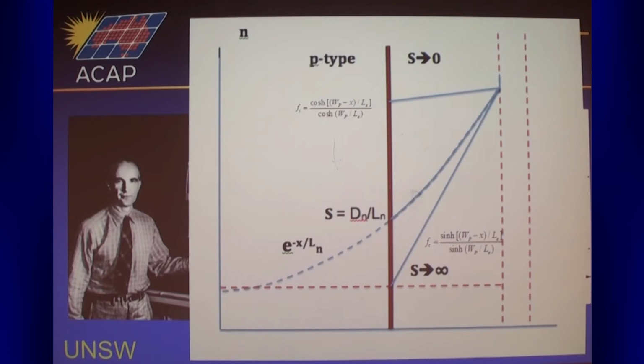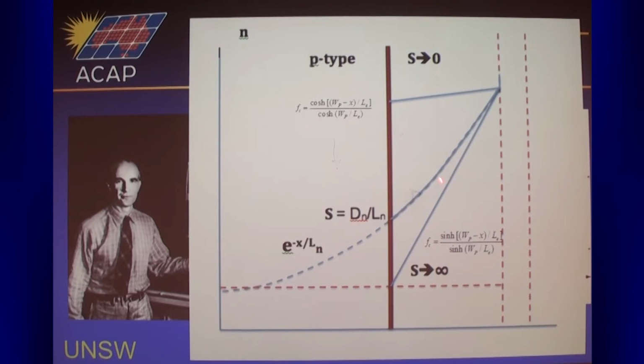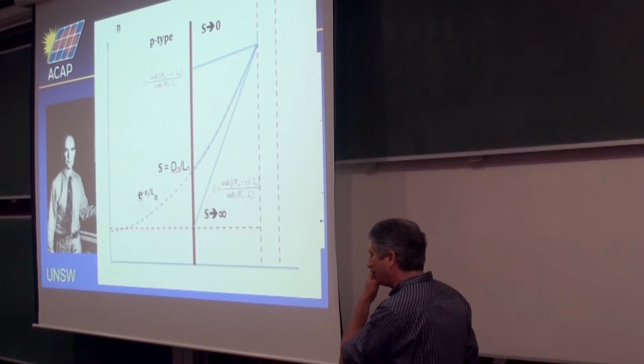But if we go back to this diagram here, it turns out, now we're talking about the carrier distributions throughout the device, but they're exactly equal to the probability that if you generate a carrier at this plane here, for example, just a concrete example, if you had a plane of generation here and you had an infinite surface recombination velocity, the ratio of this to the value here would give the probability of collection. So, we didn't know that at the time, so we were sort of thinking the current and voltage in the cell are separate, but they're fundamentally linked by this relationship.